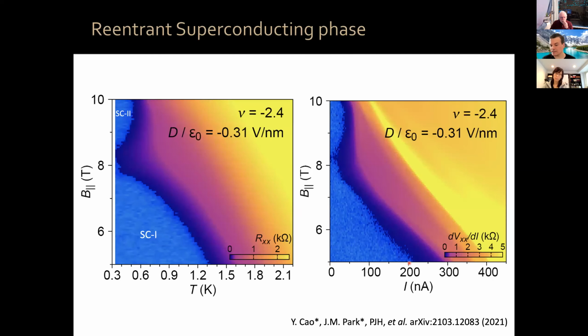The critical current as a function of parallel magnetic field, okay? Again, I'm focusing only here from 5 Tesla upwards. The critical current comes from very high down there, and it decreases, becomes pretty much 0, and then starts to grow again, okay? Now, there are very, very few systems where you have low field superconductivity and a reentrant superconducting phase at high field, okay?